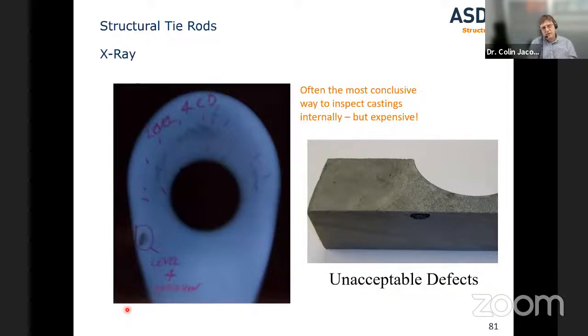X-ray is another good way of often looking for internal defects. It won't tell you any mechanical properties, but it will often uncover some issues you can't find by MPI or ultrasonic. In this particular example, you can see we have what's called shrinkage. This is where the casting hasn't cooled properly. Literally, the material is pulling away from each other, creating shrinkage cracks. And again, you have an inclusion here, a level 4, all shown on X-ray. If we cut that casting there, this is the type of defect you would see inside your casting.